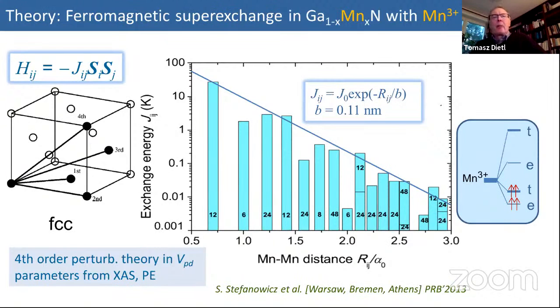parameters, a calculation by tight binding of ferromagnetic exchange. For this charge state, we do a calculation of p-d hybridization up to fourth order in this hybridization matrix element. We end up with the conclusion that the interaction is ferromagnetic and depends on distance between manganese, like we expect for superexchange, decaying exponentially with distance between magnetic impurities.